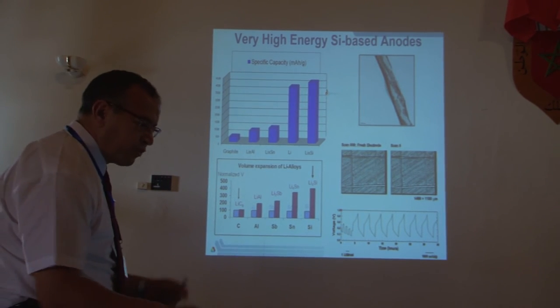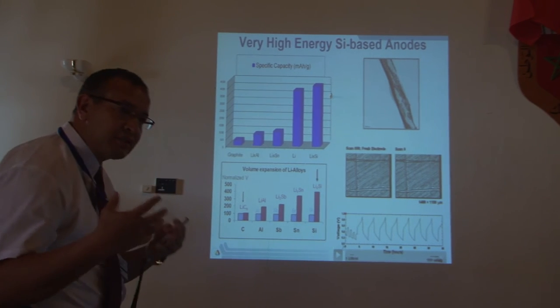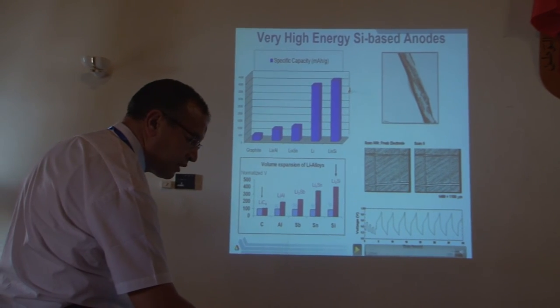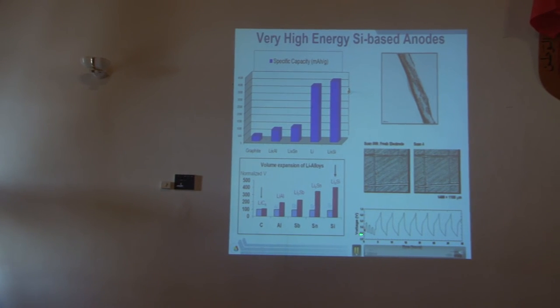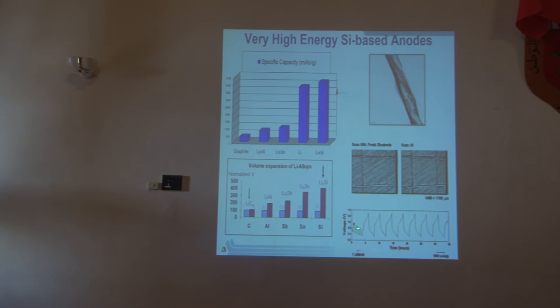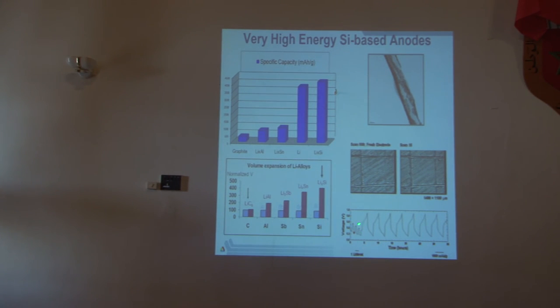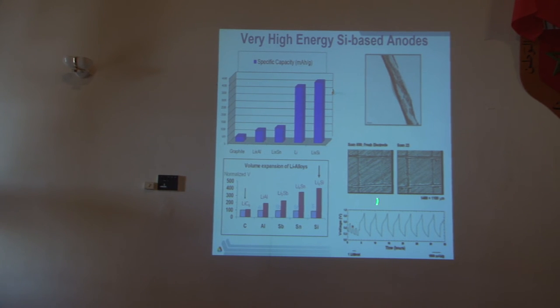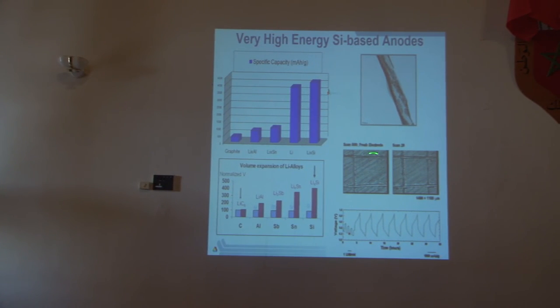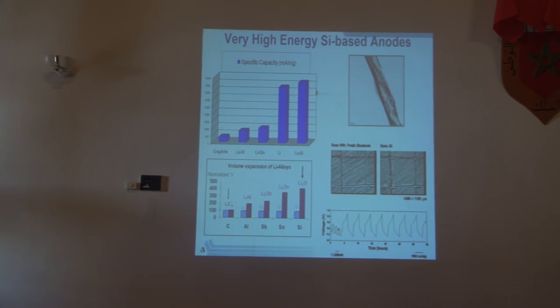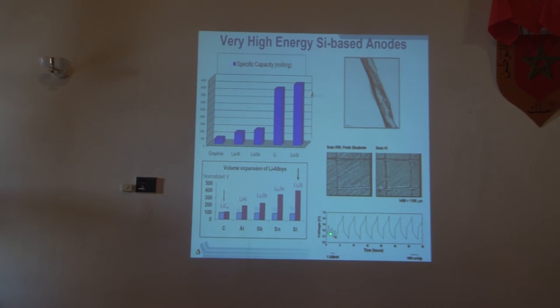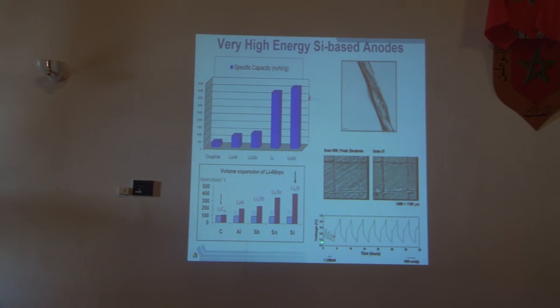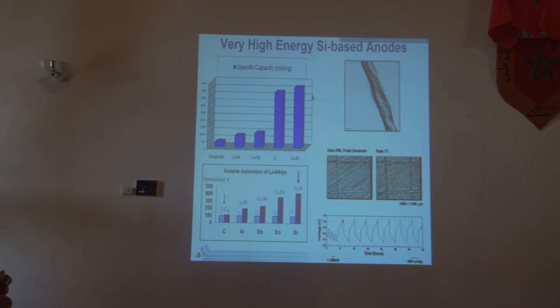And if you do it in a real electrode for lithium ion, where you basically make silicon mixed with carbon and make electrodes and run it, you have to be patient. Look at this dot. We're not lithiating yet, but once you start having the dot here start alloying lithium, please pay attention to this. This one is the reference electrode. This one is cycled, using AFM, for instance. Pay attention here, you can see that there is cracking that starts forming. So this is the first cycle. Obviously this is not possible.